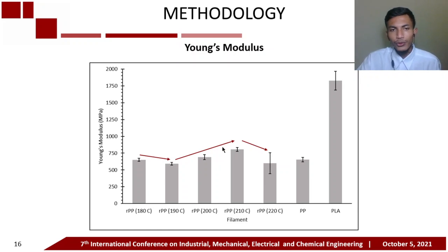The data of Young's modulus shows a similarity with the ultimate tensile strength data. The highest modulus value is at 210 Celsius. These results support the hypothesis that the operating temperature of the RPP filament is at 210 Celsius. However, an anomaly appears in the data trend in the temperature range of 180 Celsius to 210 Celsius. The modulus value appears to decrease at 190 Celsius and increase again at 200 Celsius, then reaches a peak at 210 Celsius. Finally, it decreases again at 220 Celsius.